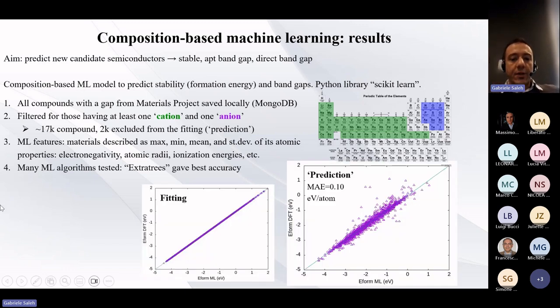On the left, the plot shows the formation energy predicted by machine learning on the x-axis, and the true formation energy, that is the one calculated at the quantum mechanical level. In the fitting, all the points lie on this green line, which is the perfect prediction. But this is the fitting, so these are the data on which the machine learning is trained. It's not assumed that they lie on this line, but they do in our case, whereas for prediction, they are a bit scattered. But you can see that most of them lie on this green line. There are a few outliers, but remember that in this plot on the right, there are 2,000 points.